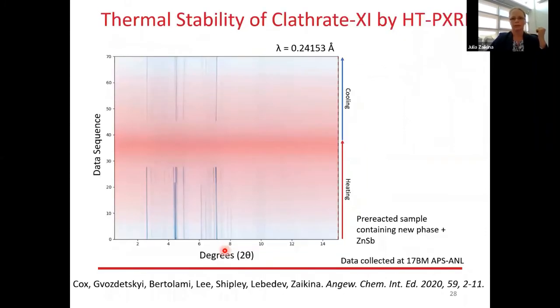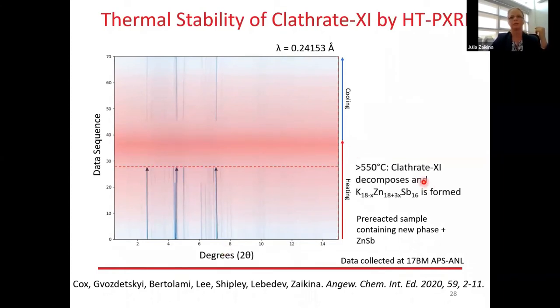So, okay, in the interest of time, I'm going to skip this part, because we again use high temperature X-ray diffraction to pinpoint the suitable synthesis temperature. And it turns out that our clathrate actually decomposes above 550. So we really need a lower temperature to synthesize this clathrate.